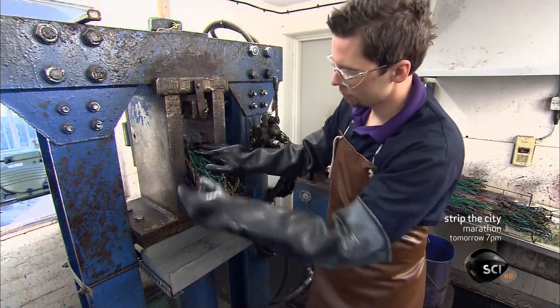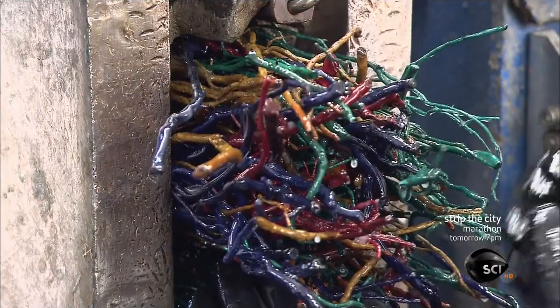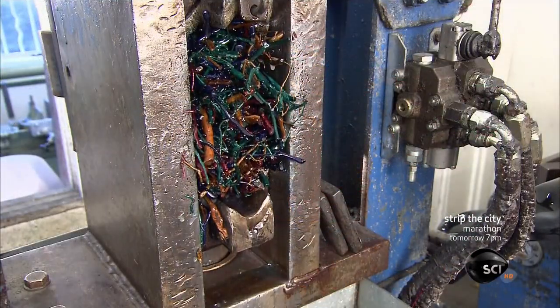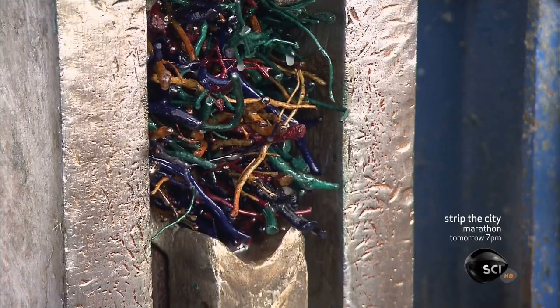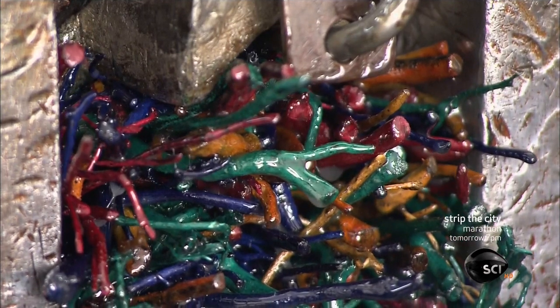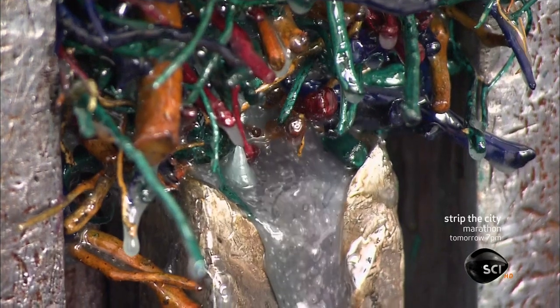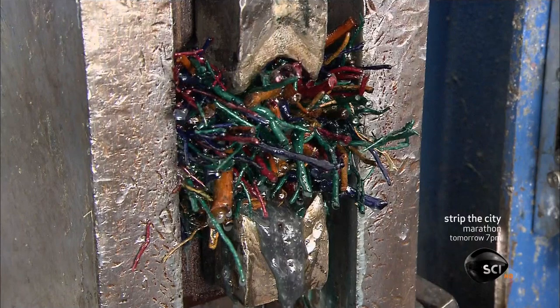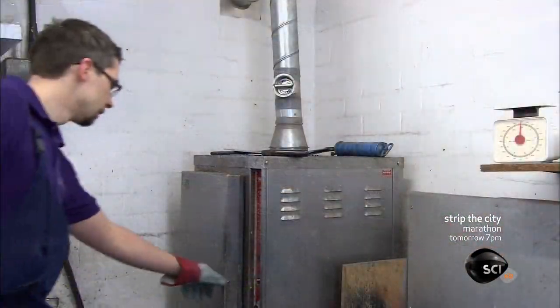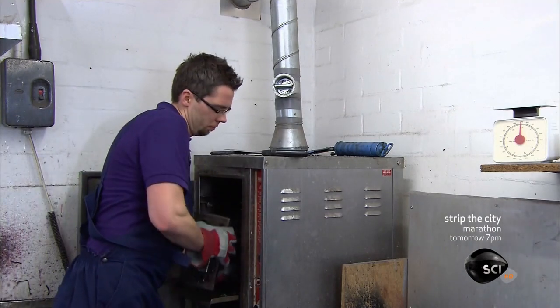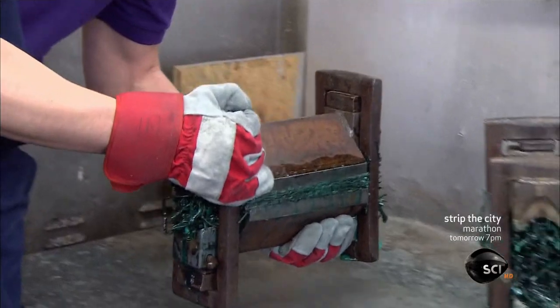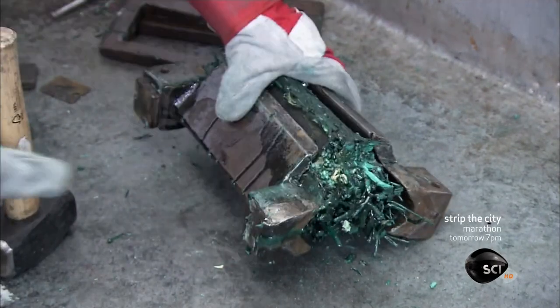They load 4 bundles between the top and bottom halves of a mold. A press then slowly closes the mold, applying 88 tons of pressure for about a minute. They clamp the mold closed and remove it from the press. Then they put the mold into an oven for an hour to cure the resin. They open the mold and remove what is now a rock-hard, resin-bonded block of heather wood.